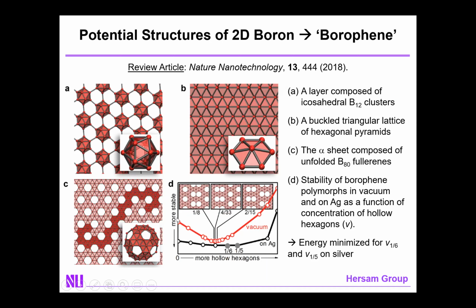And if you calculate the stability of such structures, you find that it depends upon the number and arrangement of those vacancies. And it turns out that the energy is minimized if you have 1/6 or 1/5 of the boron atoms missing from the triangular lattice. And this is further lowered in energy if you were to grow the material on a noble metal such as silver.